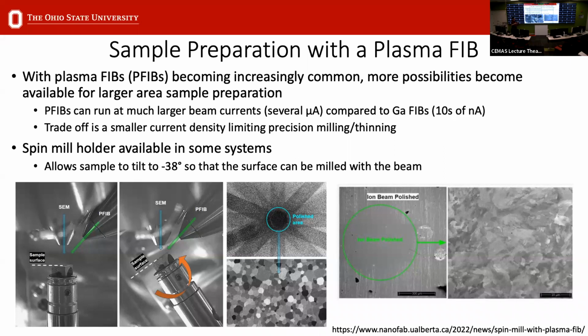So it makes it more difficult to do precision milling and thinning, which is very important for TEM preparation, which I'll talk more about later. But in some systems, there are specialized holders, such as in Thermo Fisher instruments, they have something called a spin mill holder, which actually lets you tilt your sample in the negative direction.